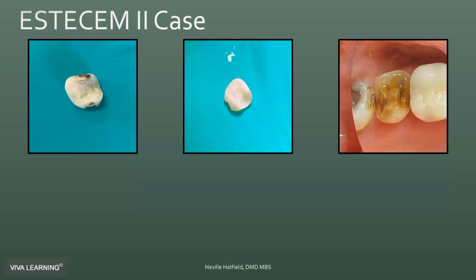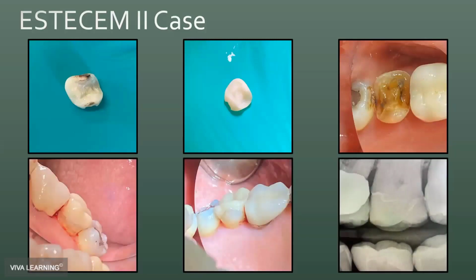I cleaned the intaglio of the crown of old cement. I air abraded everything. I re-etched with hydrofluoric acid to get back down to the base ceramic there. And then I followed the same cementation protocol that we just did in the previous case. I did a total etch technique. I used Tokuyama Universal Bond with translucent cement.